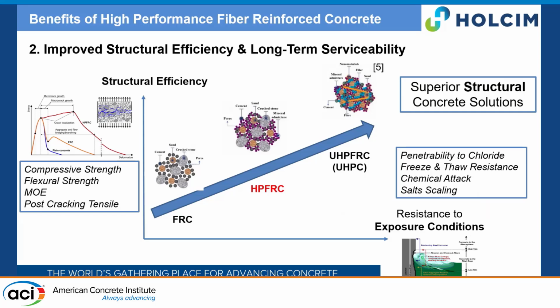Now, when we want to map out where high-performance fiber reinforced concrete lands compared to regular fiber reinforced concrete, HPFRC is right in the middle. Typically, as the structural efficiency increases on the top right, and as the resistance to exposure conditions or the durability of the material also increases, we get a stronger, better material. And ultimately, on the top right, we have the UHPC. So we work on the microstructure, we work on the interaction with the fibers, and we want to maximize the synergy. And we also look at the durability aspect, in terms of chloride penetration or freeze-and-thaw resistance, for example.